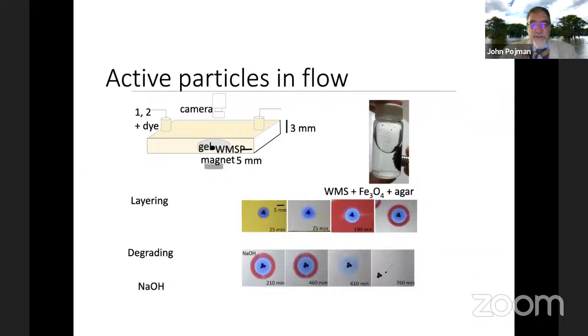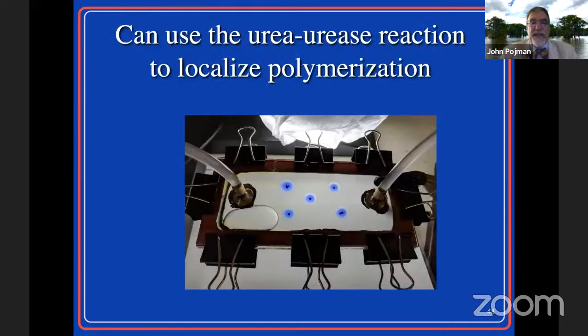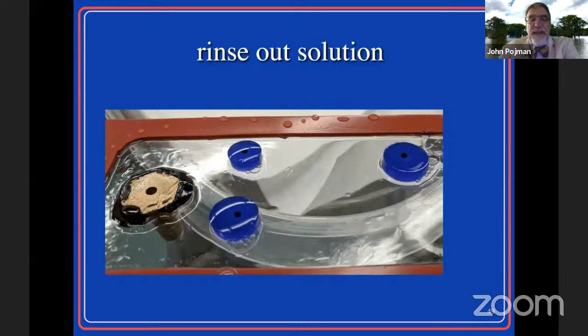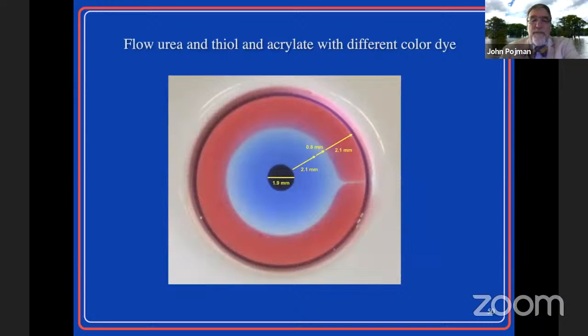Anthony's been able to put them into a flow, so he can localize a polymerization where he puts the particles. He can move those particles around, initially using a magnet. And then after they're done, I don't know if you know the term tiddlywinks, a kid's game with little discs that you can play with. These look reminiscent of that, these discs. And then by putting different solutions through, you could make different colored layers or different structures.